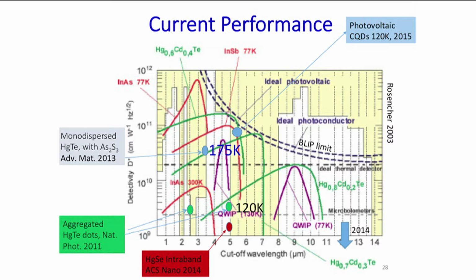They also give you a recombination. So when you photoexcite, you create another carrier. Let's say an electron might recombine with a hole that was thermally generated before. So the lifetime gets very short. The efficiency becomes very low. But the other problem is Auger recombination, which is where the recombination rate is growing in a nonlinear fashion with the thermal density of carriers.